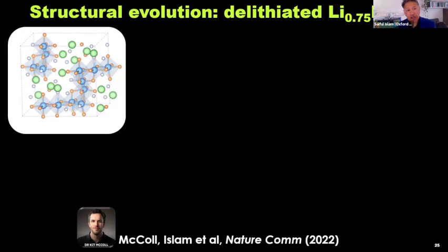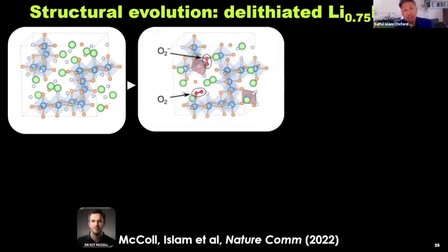I'm showing you the lithium ions in green, the manganese in blue, and the anions in orange and light grey. What we're seeing straight away is that there is manganese migration, shown in a brown octahedra, but coupled to that is some oxygen-oxygen dimerization.